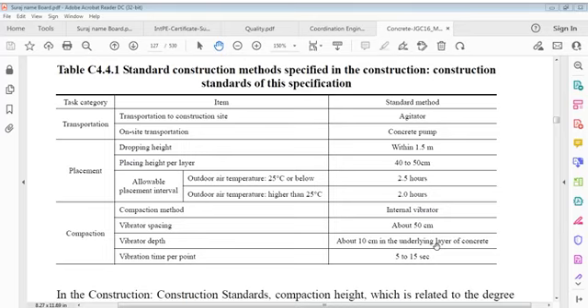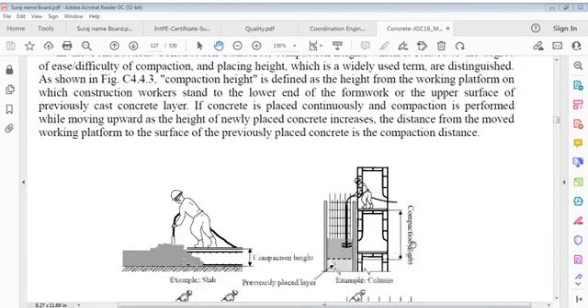It's very important information. I repeat, transportation category: transportation to construction site, agitator use, and on-site transportation, concrete pump. Placement is dropping height 1.5 meter, not more than that. Placing height per layer is 40 to 50 centimeter, or 400 to 500 mm, as we usually take. Allowable placement interval: outdoor temperature 25 degrees, 2.5 hours; outdoor temperature above 25 degrees, 2 hours. In compaction method, internal vibrator spacing about 50 centimeter, vibrator depth about 10 centimeter in underlying layer of concrete for interlocking. Vibration time per point is 5 to 15 seconds.